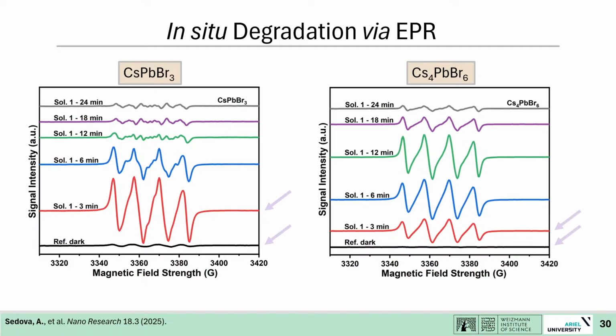By measuring EPR spectra every 3 minutes, we could closely see the changes that are happening. By computational means, we can fit these spectra and basically identify what radicals are contributing to the decomposition. Also, this technique is very efficient in studying electron transfer in the case of semiconducting materials.